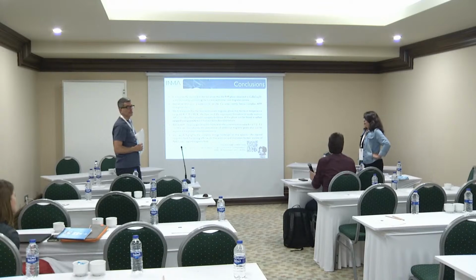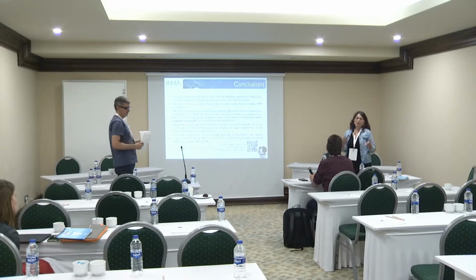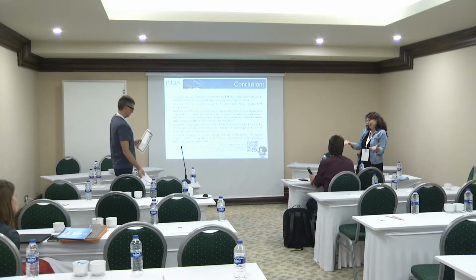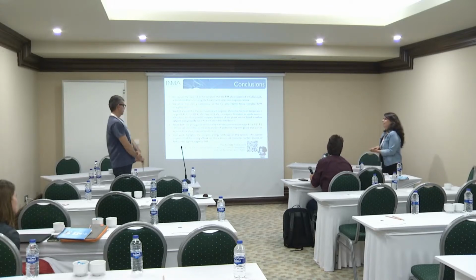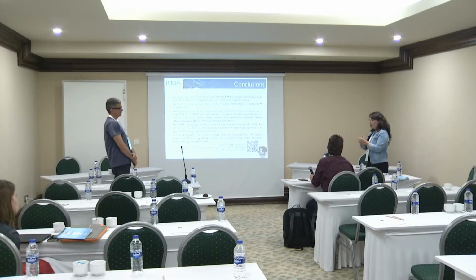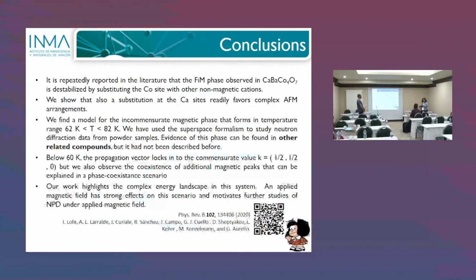No, the first guess, of course, was to look for the 1/3, 1/3, 0 because this is expected for this kind of triangular layer arrangement, but that didn't fit the data at all. So we said, okay, we have to expand our search for the propagation vector. So I think that the interaction between the layers is playing a significant role, because if they were isolated, you would have that order for sure. Thanks.